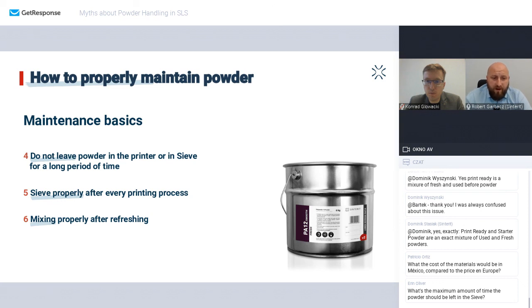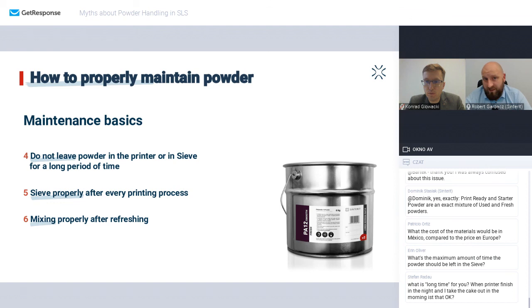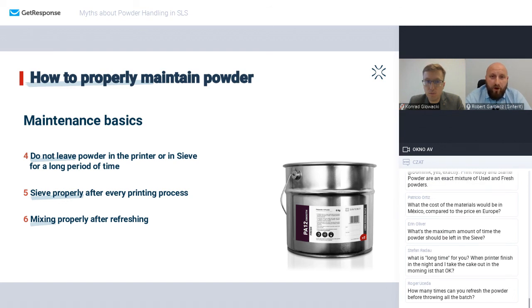You need to sieve the powder after every printing process. Sieve properly, the sieve will do the job for you. If the sieve does its job, the powder will be properly prepared for the next print. Then you add a refresher, which is the sixth point: you mix it with a dedicated amount of fresh powder and shake the bucket for about 20 seconds. So, 6 super important rules to maintain your powder.